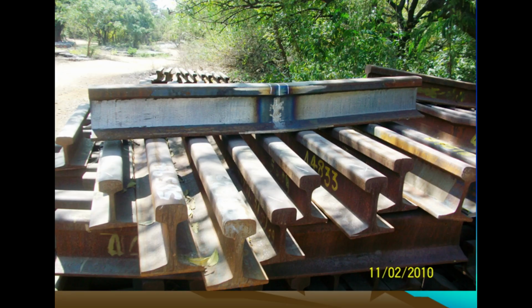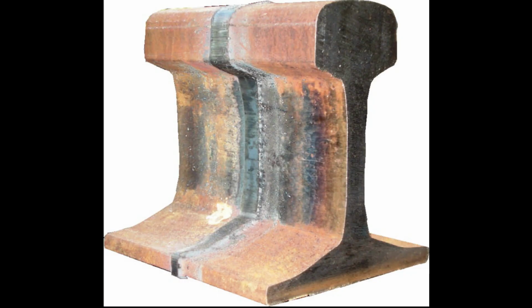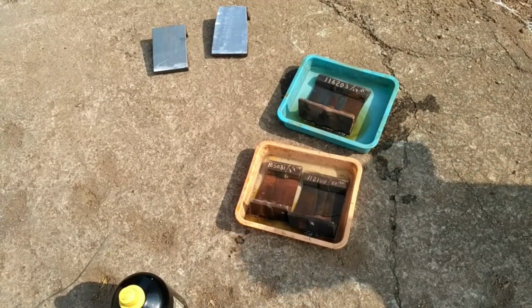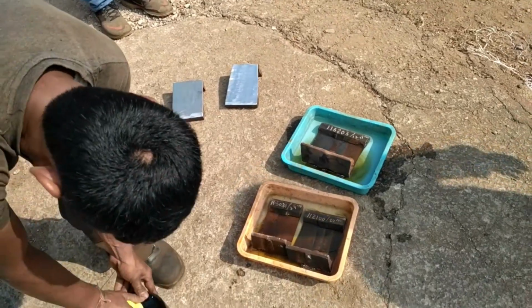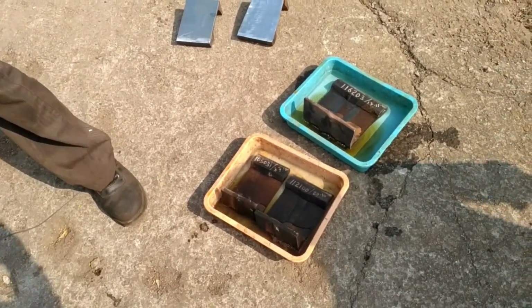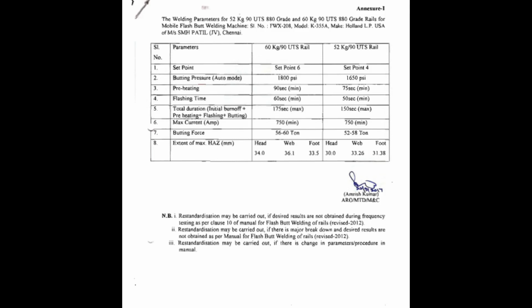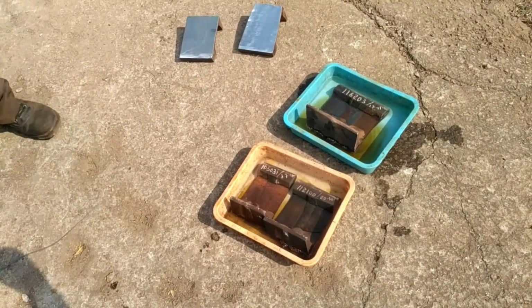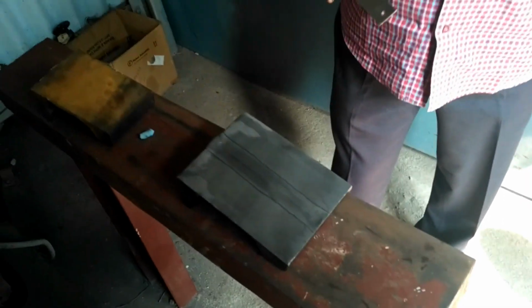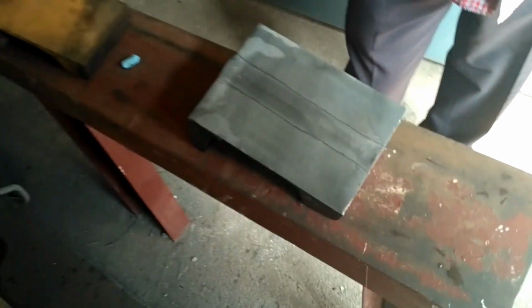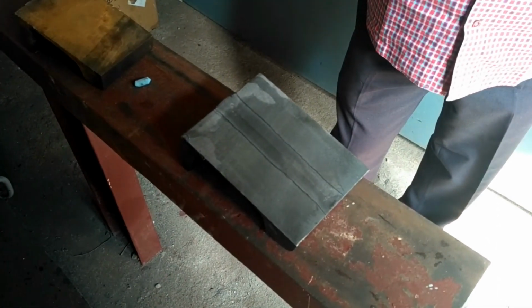Then coming to macro examination, you will examine the visible heat affected zone, which shall be normally parallel from head to flange, that is symmetrical in shape about the weld line, and fall within the range between 20 and 40 mm. The permissible deviation between the maximum and minimum shall not exceed 5 mm. And there shall be no evidence of lack of bond, inclusion, cracks or shrinkage, etc.